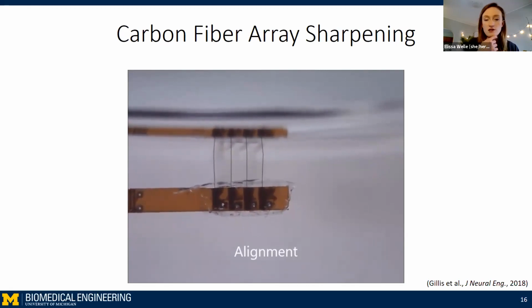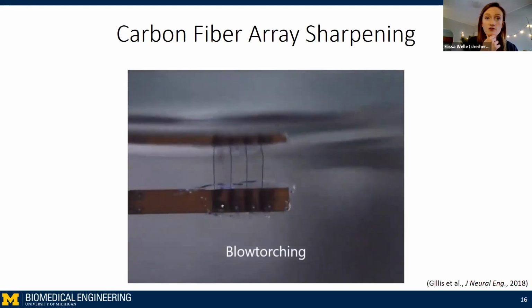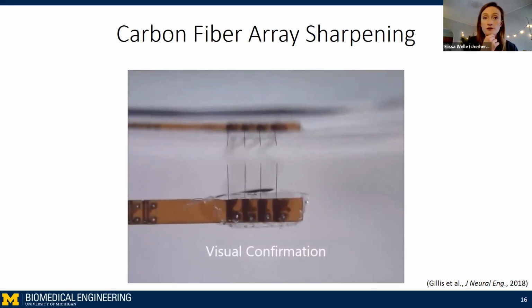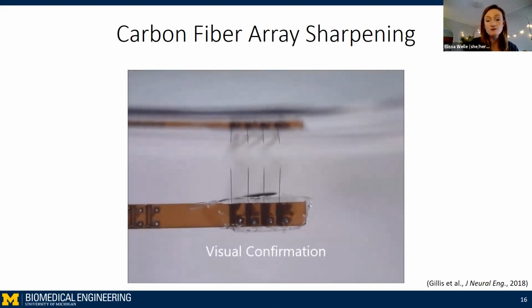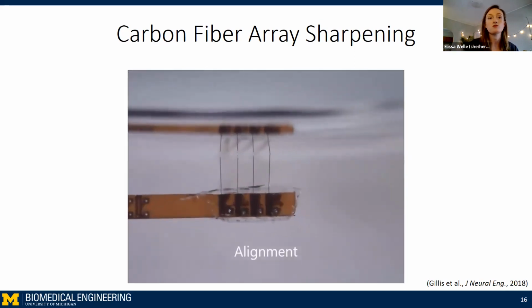And what you're seeing here is we're looking at the reflection of the array underneath the water surface so that we can align the tips directly to the water surface so that they can be sharpened by a small butane flame while the rest of the array stays intact. And the ripples of the water that you saw there briefly were the movement of the butane flame.